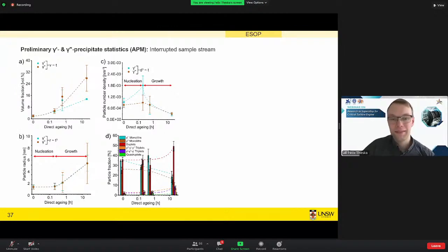Sure. Please remind me if I miss any part of the questions. So the first one is the stability of the DO22, which is the gamma double prime. Yes, gamma double prime, and that's actually less stable than the L12. It provides a lot of strength for temperatures up to 650, 700 degrees centigrade. But above this, you get a transformation of gamma double prime into the delta phase, so any strengthening effect is completely lost. That's the big disadvantage of this alloy 718, that you cannot use it at much higher temperatures than this. So these really high temperature resistant superalloys, like up to 1000, they all use gamma prime, which is L12 ordered.